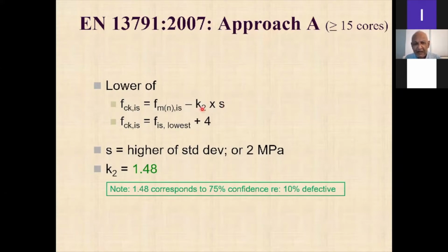And then now we put 1.48 here rather than 1.64, which is what we use for concrete supply, right? And of course, the in situ characteristic strength should be the lower of this one or this one, right? This S value, you can actually calculate the S value, right? Or if it is less than 2 MPa, you have to use 2 MPa, right? And the K2 value that is used is 1.48, right?